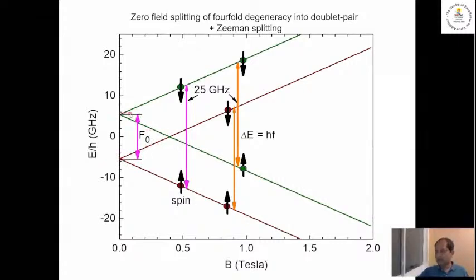Now, if you have sublattice degeneracy being lifted, then you have 2 sets, right? You have the green set and you have the brown set associated with different sublattices. And this splitting over here could be a constant value. And then you could get a new kind of resonance, which is going from a spin for one sublattice to a spin of the other sublattice, right? So you could get this new kind of transition, the purple one. And the thing about this purple transition is that as you go to zero magnetic field, there's still a gap. And so the splitting doesn't go to zero, right?